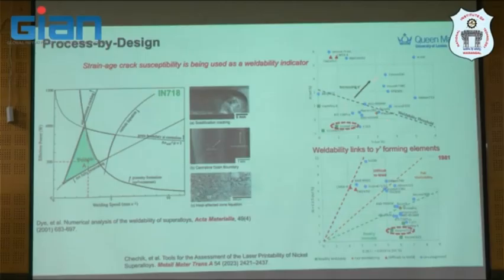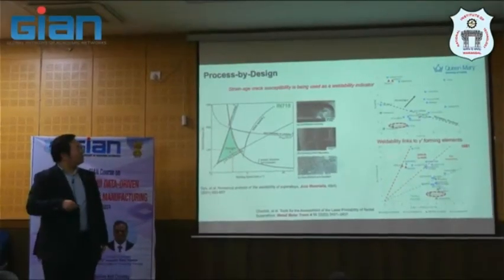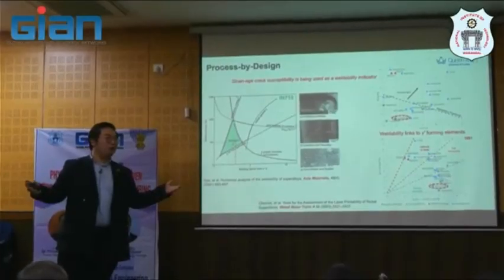So when gamma prime is increasing here, they believe it gets worse. But I'm quite interested in this diagram because there's no gamma prime during 3D printing, right? In powder, have you observed gamma prime? No. But in this case, probably relevant, yes. But I don't know why people still keep citing this paper, because in welding you have the parent material. Parent material is a fully homogenized structure when you weld it, right? That means that material contains some gamma prime after homogenization. So gamma prime is relevant, but why? This is my speculation and also question. Why in AM do people still refer to this diagram, even though we don't have gamma prime at the starting condition?